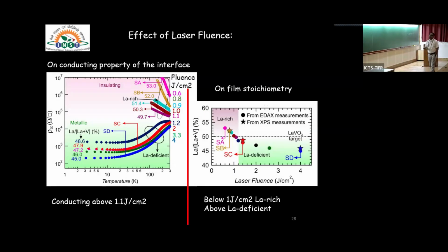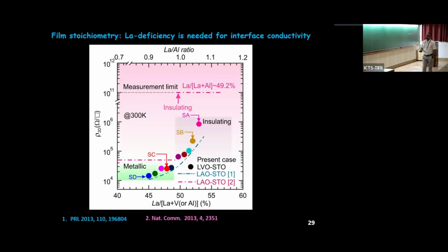Then we started calculating what is happening. If you plot the laser fluence as a function of the ratio of lanthanum and vanadium, you can see this area is the lanthanum rich area, and this is the lanthanum deficient area. In the lanthanum deficient area, you get conducting behavior, and in the lanthanum rich area, you see insulating behavior. People had already seen a similar thing in the LAO/STO system. So this dotted line is, yeah, please.